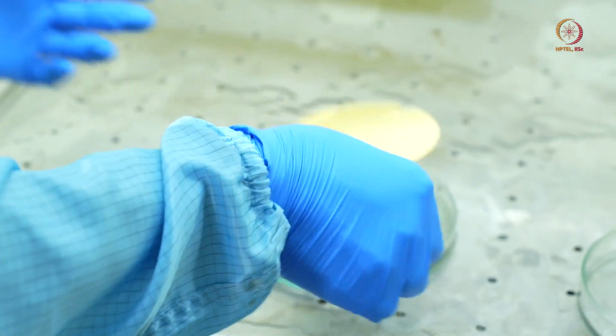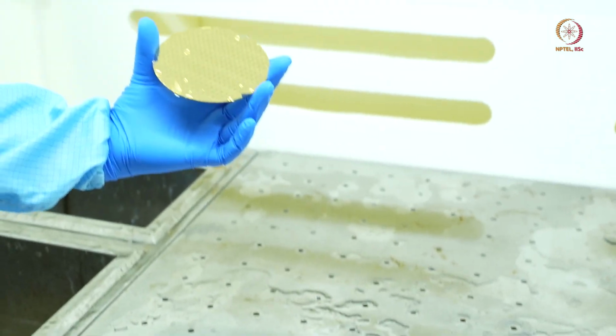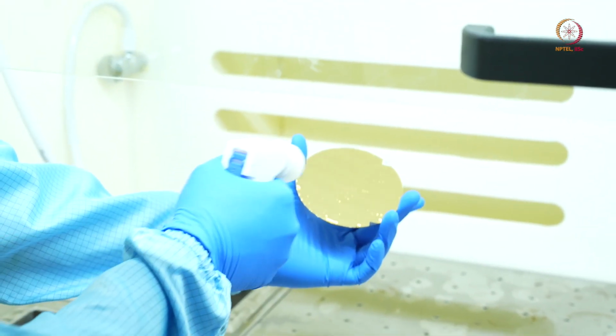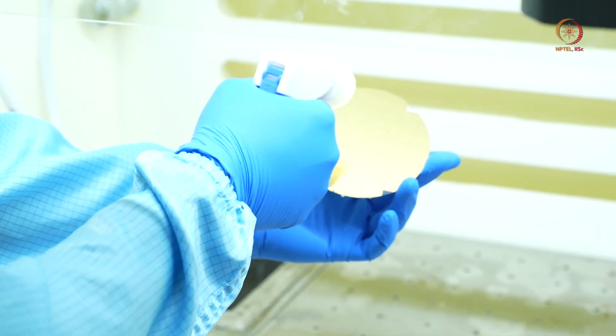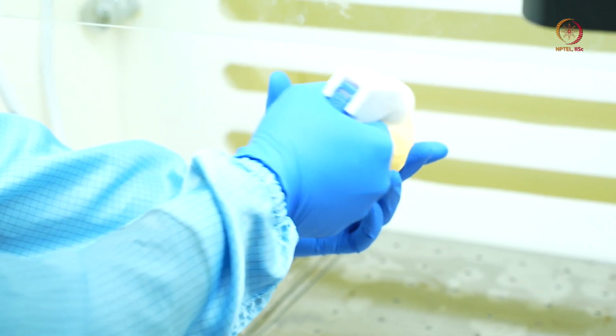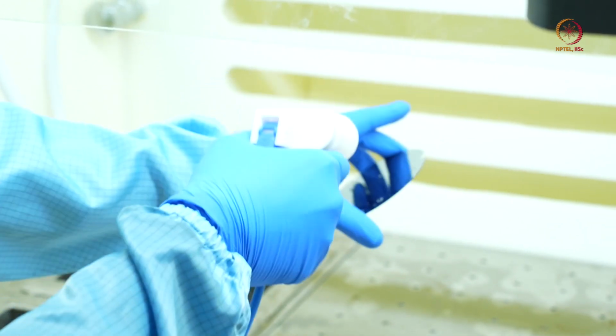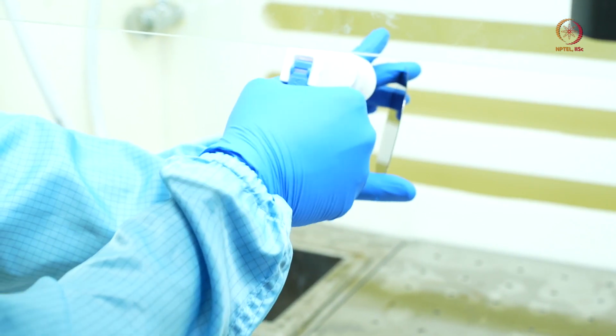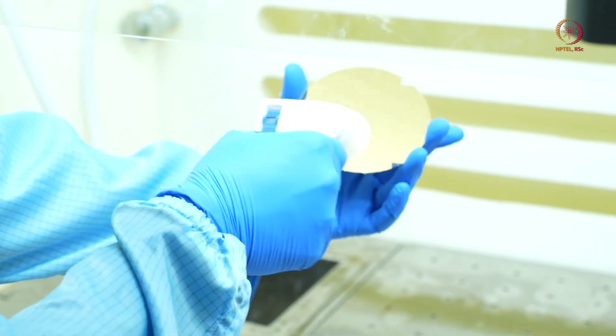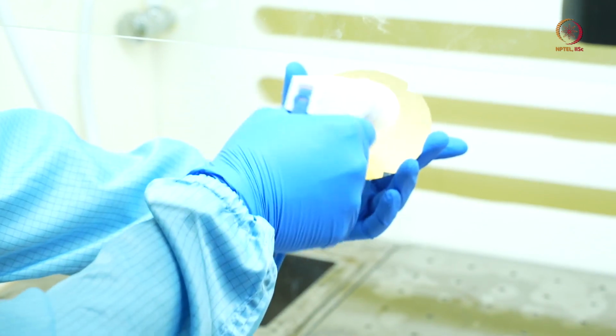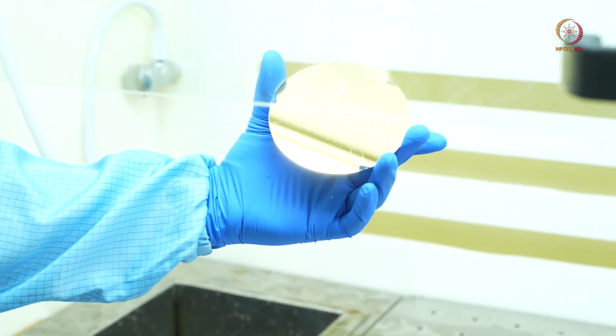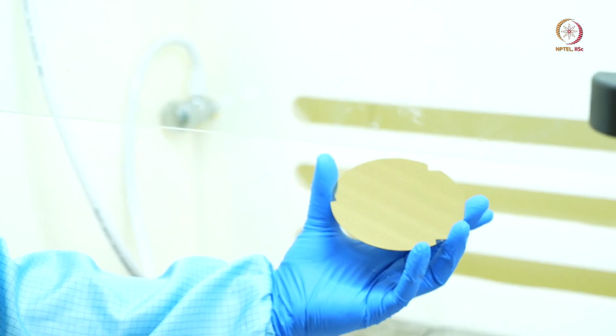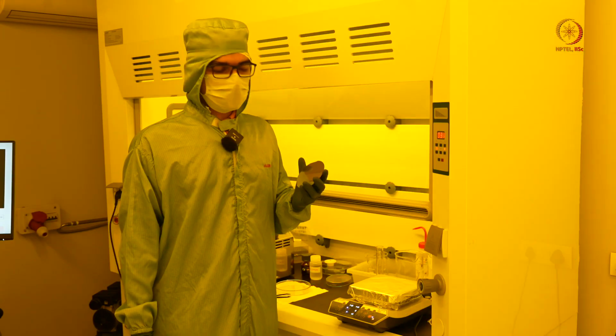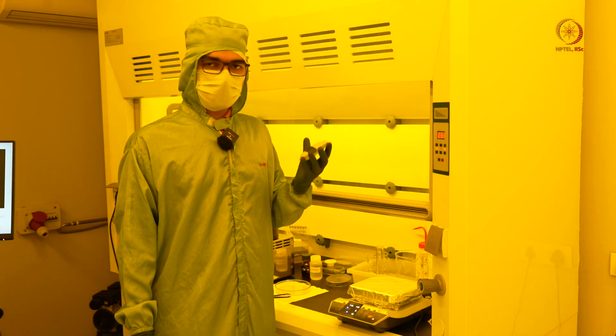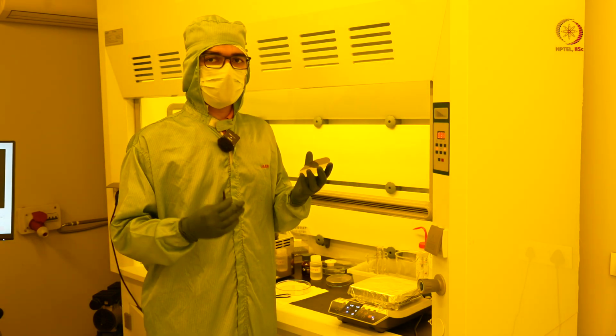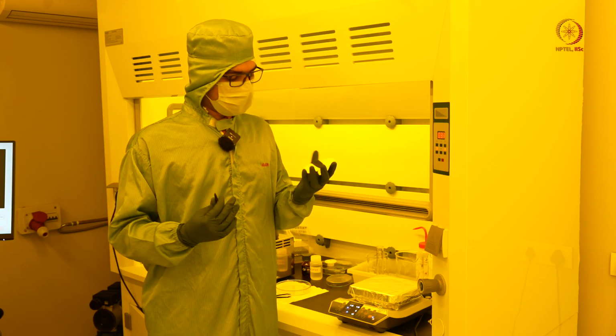And the next step is to blow dry the wafer using nitrogen. So we have a nitrogen gun here. So this step makes sure that the water is gone without leaving any marks when drying. Yeah, so the sample is clean now. So we will keep it for dehydration bake, which is a very crucial step before we spin coat photoresist. Okay, so it's very clean now.